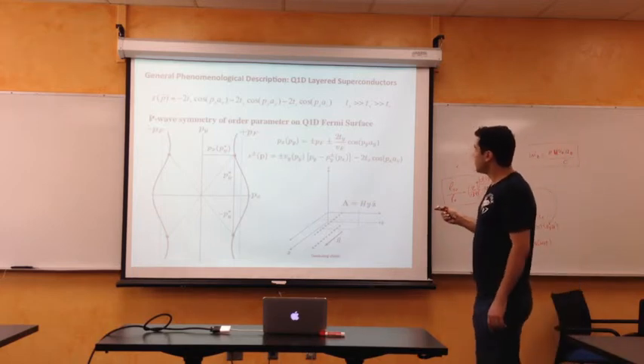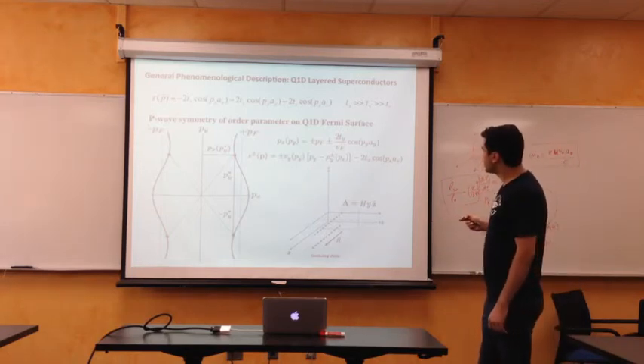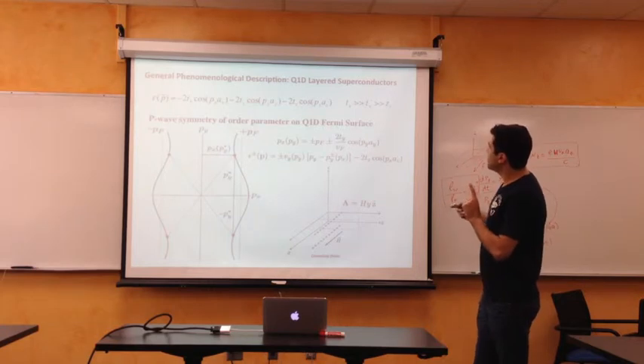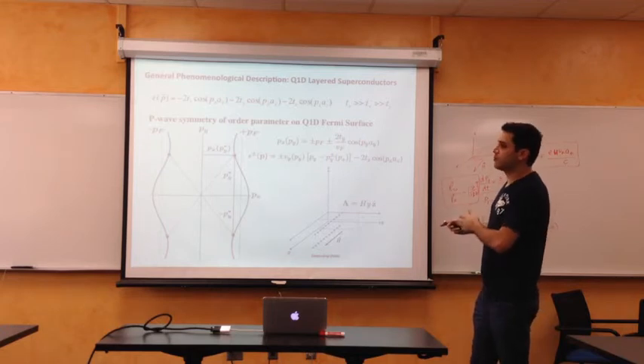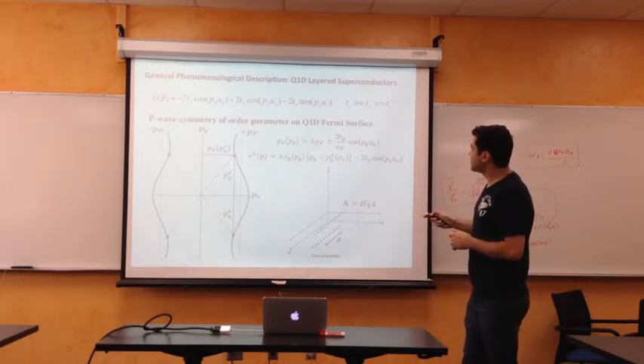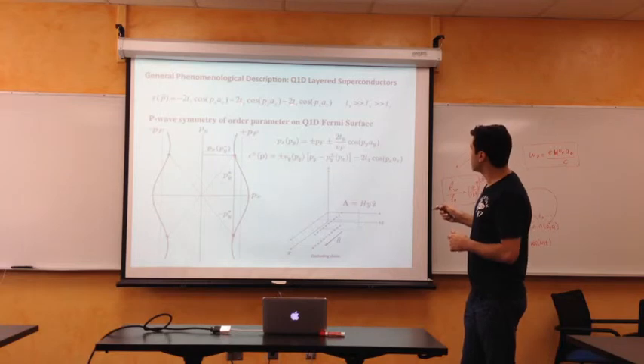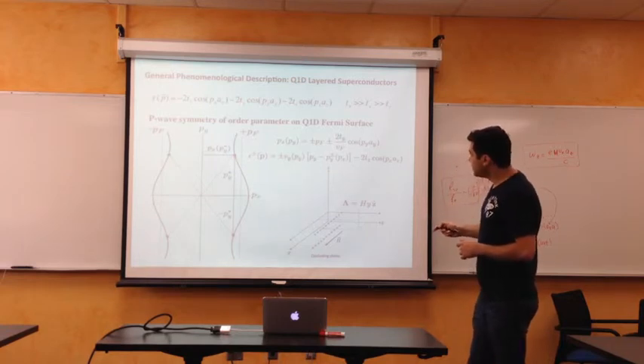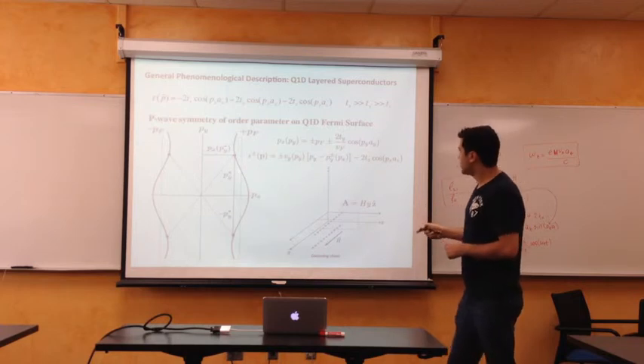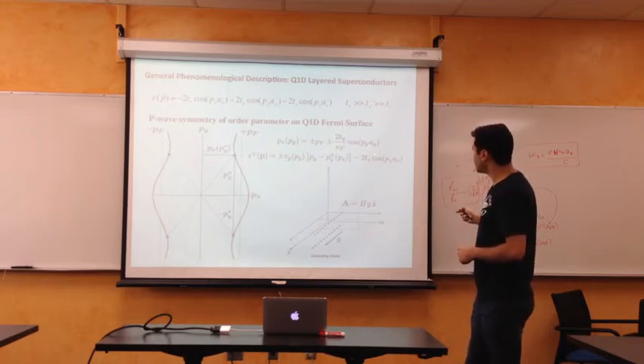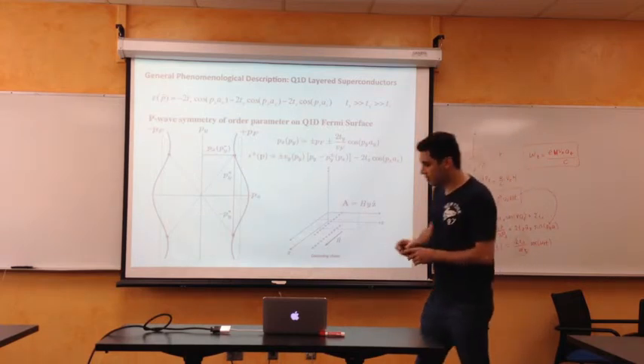So based on this linearization, remember here the hopping integrals are different in this compound by orders of magnitude. Because Tx is much larger than Ty, much larger than Tz, we're able to linearize the anisotropic electron spectrum on these sheets of the Fermi surface this way, and then we get the Hamiltonian.